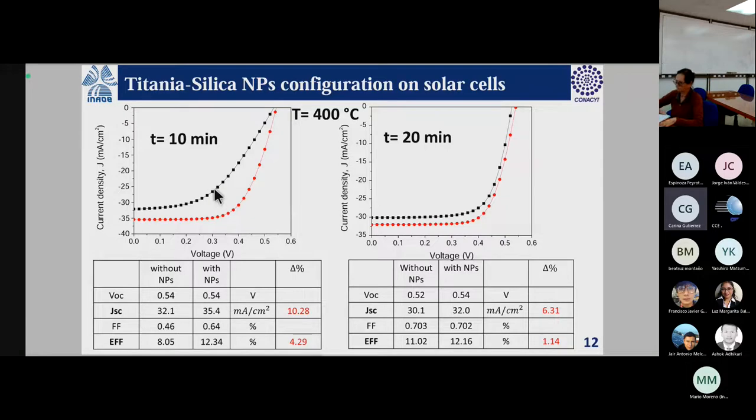and we can see the response. For example, when we have solar cells without any treatment, the red and the black line correspond to solar cells that don't have the nanoparticles, the raw solar cells. But when we apply the nanoparticles over solar cells and apply the thermal treatment at 400 Celsius degrees for 10 minutes, we can see that the current density is increased,